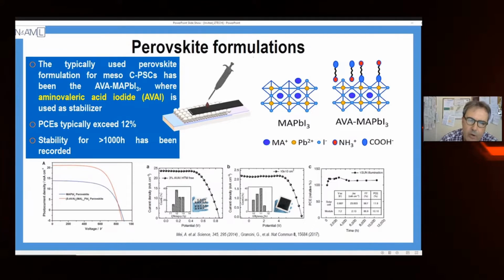It is now a composite perovskite with this material, which helps. This here is the starting material of methylammonium lead iodide. And I suggest this solution because now we improve the interface between the perovskite and the carbon electrode. And finally, you can see we get a different performance for the solar cell. Here is the case that we don't have this additive, and this is the case that we have this additive. So it really helps because it improves the interlayer between the carbon and perovskite, giving a better interface between these two different materials.